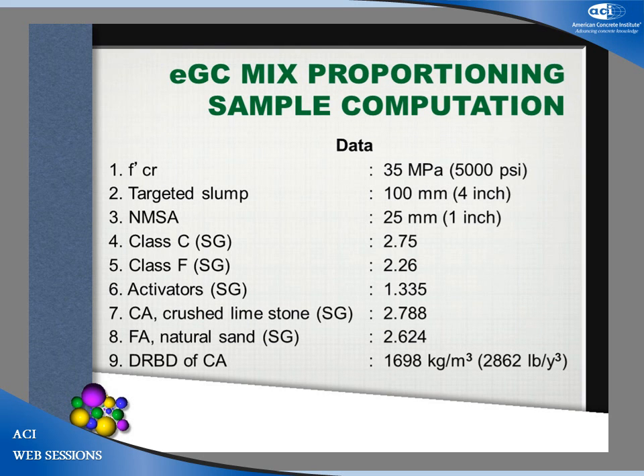Let's see the sample computation, a similar method to ACI 211. And this is the sample data. If you require 35 MPa compressive strength concrete, 5000 PSI, and the target slump is 100 mm, 4 inch, our nominal maximum size of aggregate is 1 inch, ASTM number 57 limestone, and here is the specific gravity of the different ingredients. And dry rodded bulk density is 1698 kg per cubic meter, that is 2862 pound per cubic yard.